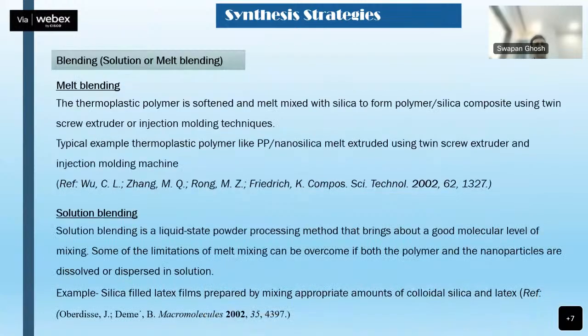Now blending: the first one is solution blending and melt blending. There are millions of examples available here, but just to say, a thermoplastic polymer is usually softened and mixed with silica to form a polymer-silica composite, and then that can be extruded through an extruder, or an injection molding machine can be used to mix those two, and then finally extrude it to give some shape of articles and so on. A typical example is polypropylene with nanosilica, which can be extruded to form a composite where you can see the silicon oxide particles inside the polymer matrix.